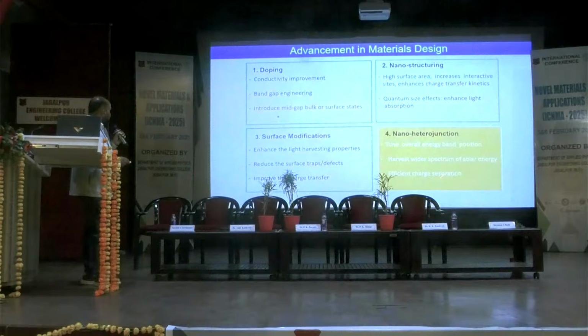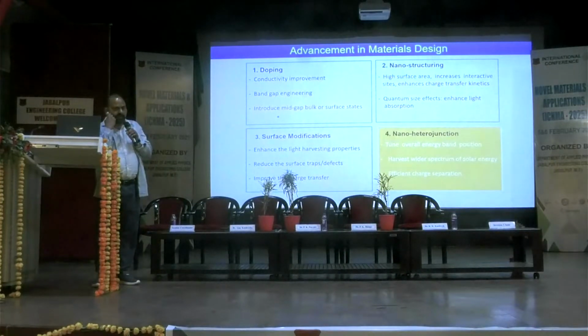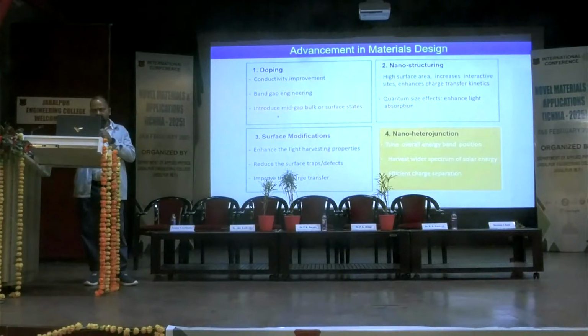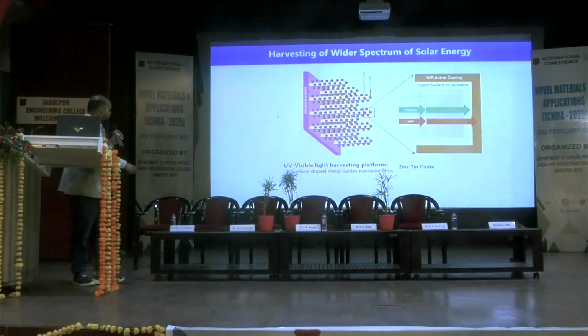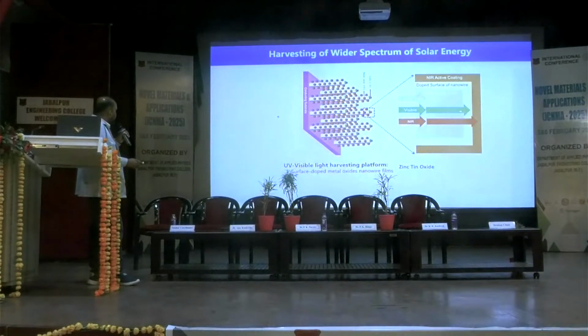So further, we are now thinking about developing nano heterojunctions so that we can tune the energy band gap. The requirement is that we are still stuck with the UV segment and some part of the visible light. But I said more than 50% lies in the NIR segment. So can we also target harvesting some of the NIR segment, which may improve the overall performance? For the last almost 4 to 5 years we have been working in this direction, and this was our philosophy. Can we develop a structure which has a 3 layer kind of system? One layer can at least take the UV light, another can harvest the visible, and the last can harvest the NIR segment.